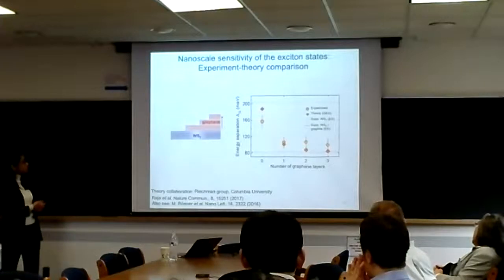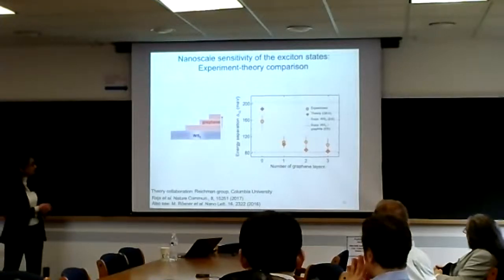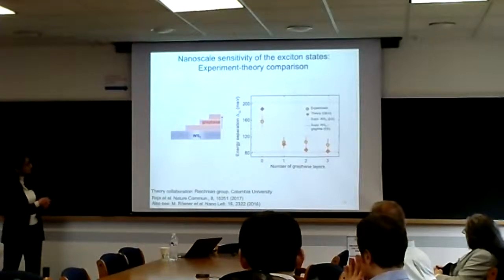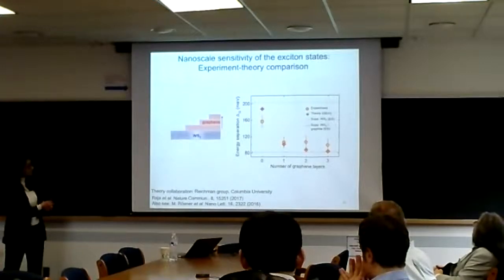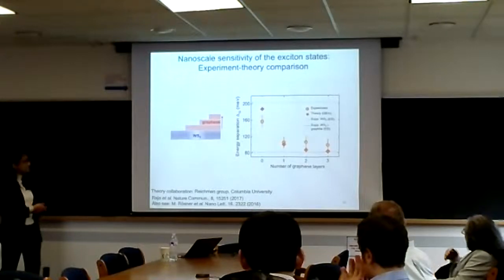Now, in this case, we're plotting delta 1,2 on the y-axis and the number of graphene layers on the x-axis. If you have no graphene layers, you have this delta 1,2 of about 160 meV. The experiment is in circles. And the moment you add a layer of graphene, this goes down to 100 meV. And after that, experimentally at least, the effect more or less saturates immediately.